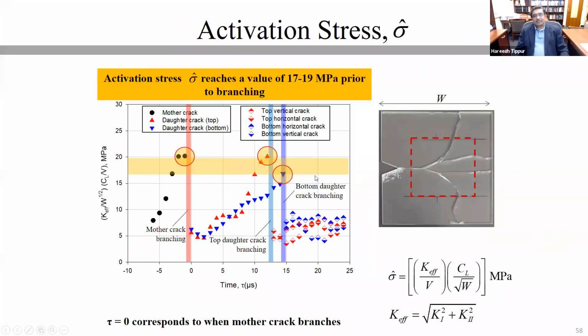This activation stress that I pointed out in the previous geometry was again plotted. And you see that that value again reaches a number somewhere between 17, in this case slightly higher than 19 megapascals. But the two daughter cracks branched at a value which is approximately in the 17 to 19 megapascal range. So we still believe that this parameter may have some value in the long run in understanding the fracture behavior itself.